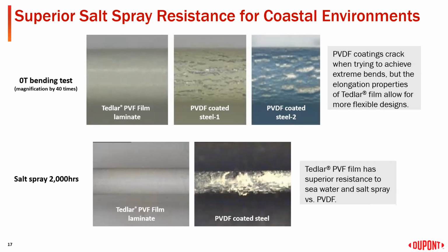You can see bottom left, the Tedlar film laminate, no issues on that bend, still fully protected. The PVDF coated metal is corroding pretty badly because it was cracked when it got bent. And that's the same thing that happens with those pinholes as well. To have that type of testing to really be able to know, and especially salt spray, like we're talking about with those coastal environments. Yeah, that's what we check for, is how is it going to do in the worst possible environment.